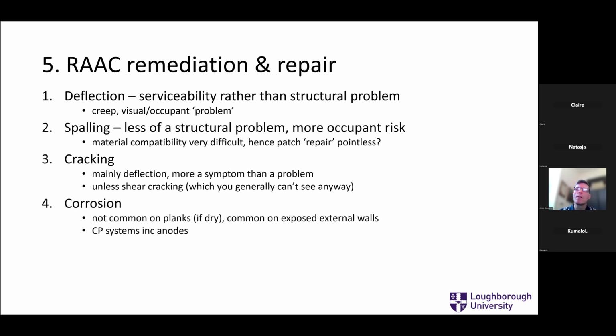Corrosion, there is some corrosion in the roofs, but not enough yet to warrant structural reduction in capacity. There are some in exposed walls. RAAC is used in some hospitals on the walls, and they're not waterproofed. So these things have soaked up water for decades, and there's some quite serious corrosion on some of the walls. You can address that. Cathodic protection systems, sacrificial anodes, hybrid anodes have successfully shown they can stop that corrosion on